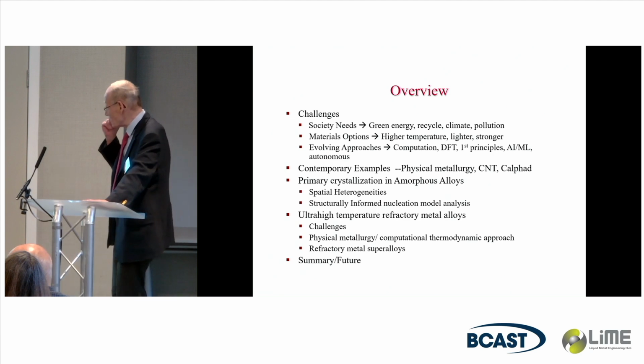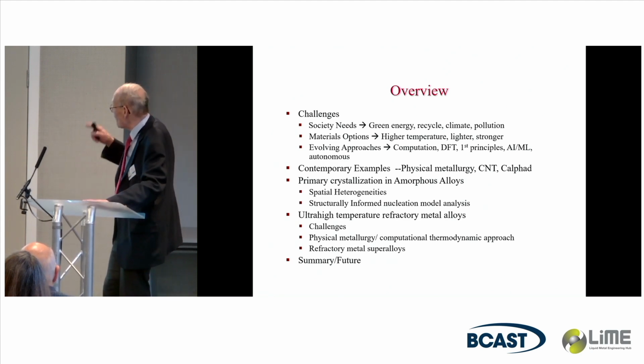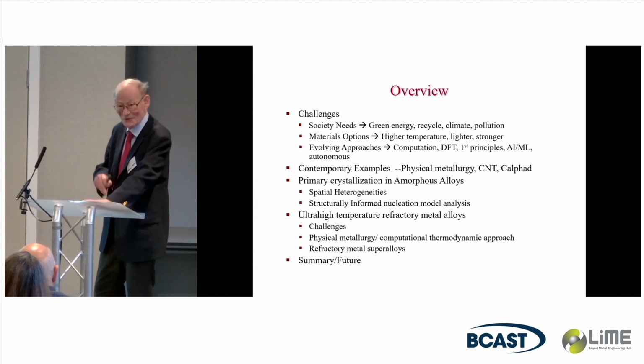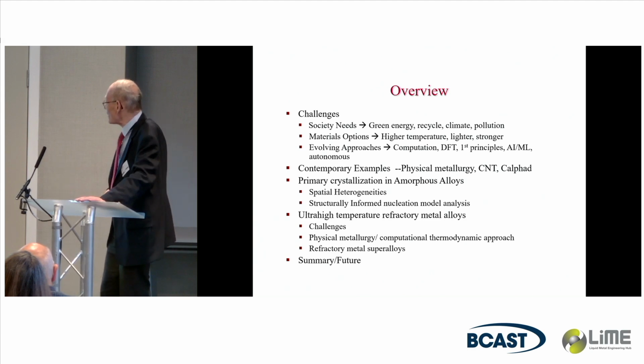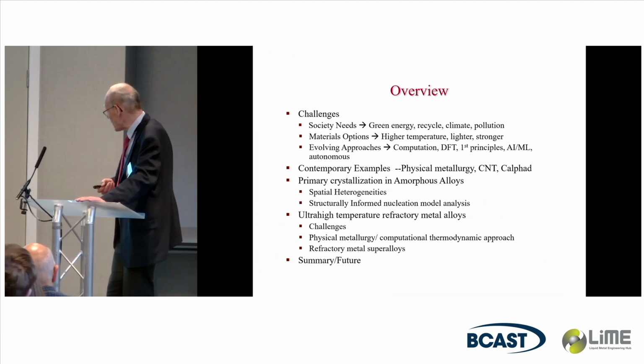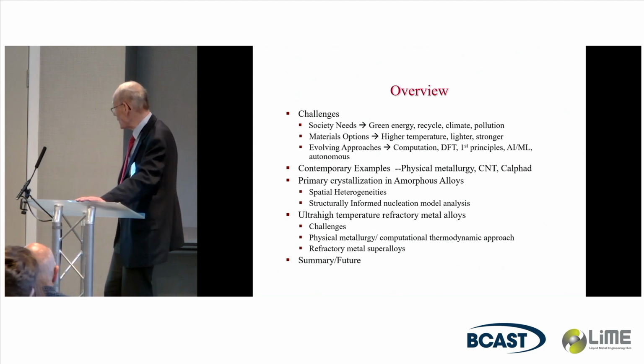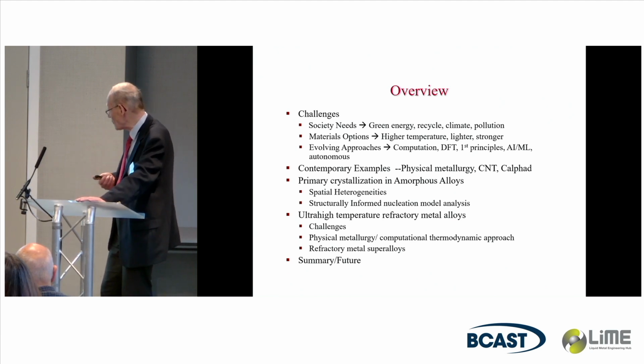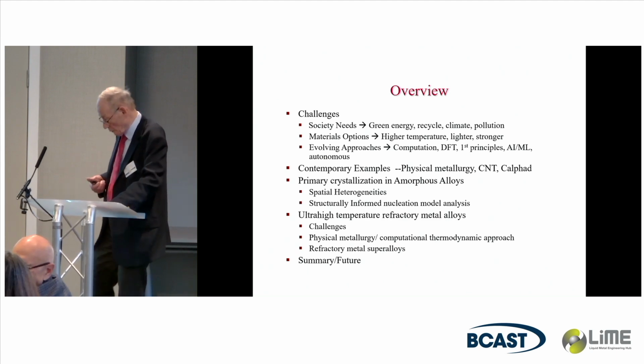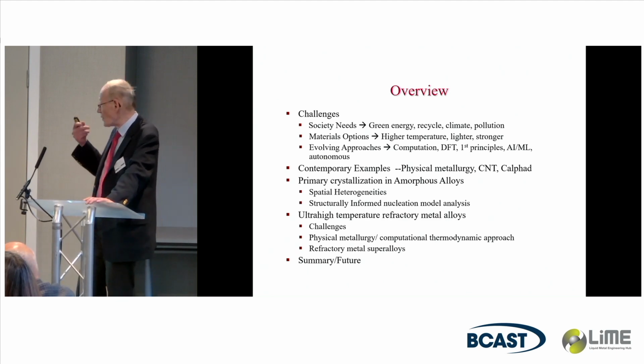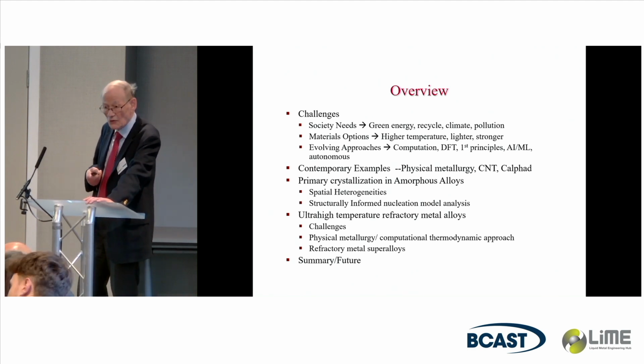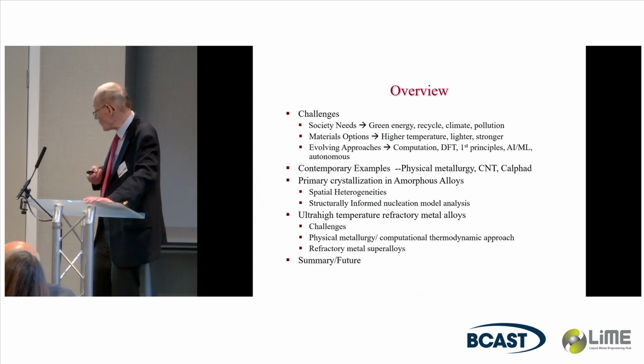And so I'm going to share two contemporary examples where I've used classical physical metallurgy, the strange field that's not so popular anymore in the States, and conventional nucleation theory and CALPHAD to show how you can really advance the field. The first example deals with primary crystallization in amorphous alloys. This includes both aluminum and iron-based systems. One of the key points here is to recognize that these solid solutions or amorphous phases are not homogeneous on the atomic scale, but there are spatial heterogeneities. And recognizing this allows us to understand the nucleation properties.